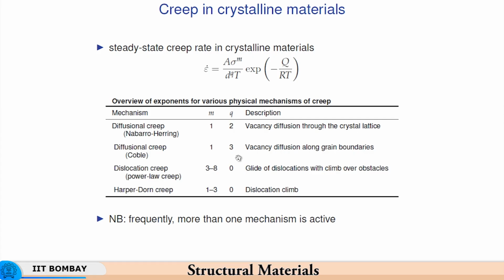Now, this diffusional creep is through the crystal. So, the crystal area is the one that is important. So, Q is 2, whereas diffusional creep is along the grain boundaries. So, vacancy diffusion along grain boundaries. So, the surface area of the grain comes into play, and that is proportional to the R cube, that is the cube of the grain radius. So, that is the reason why these exponents are different for Nabarro-Herring creep and Coble creep.